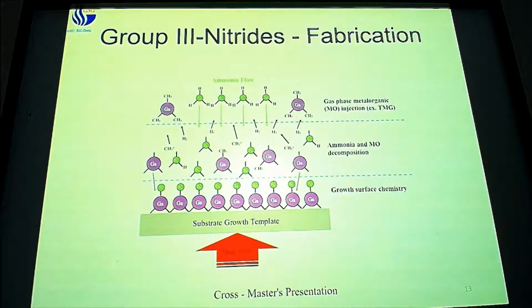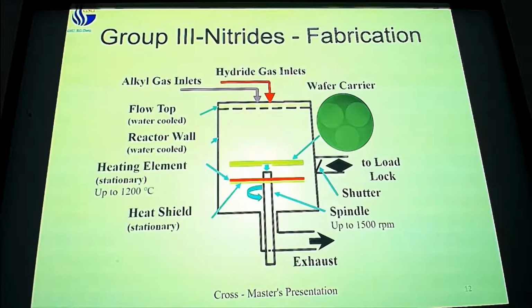Right above the wafer carrier, the templates, we have this area where there's high energy, high temperature, and the ammonia breaks down and the TMG breaks down, so we can combine the nitrogens and the galliums to make gallium nitride. So what is the high temperature? There is a heating element underneath, so in this case, radiant heat. Just radiant heat, yes.